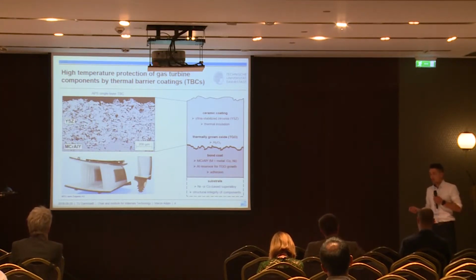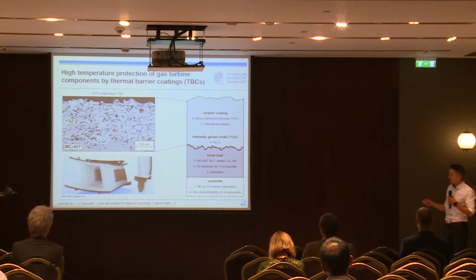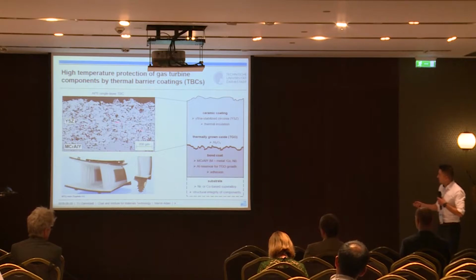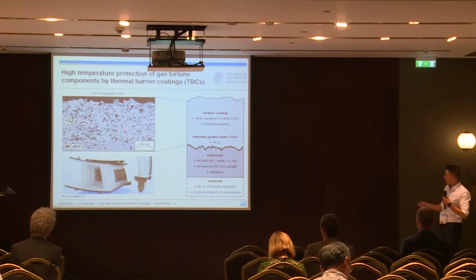We need a ceramic coating with a low conductivity to decrease the temperature from nearly 1,200 degrees Celsius at the surface to 950 degrees Celsius at the ceramic-bond coat interface. Here on the left side, we see a typical picture of a ceramic coating produced by atmospheric plasma spray. This system is called a conventional single-layer TBC.